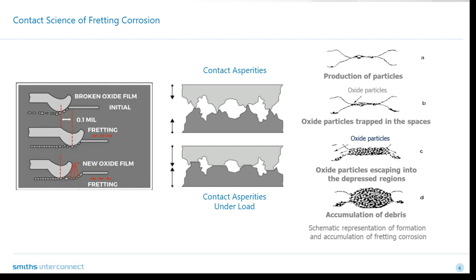When a fretting motion is induced, the noble coating, gold, is worn away and the nickel is exposed. As the fretting repeats, the oxide layer is wiped away, new oxides form, and the cycle begins again. As the process continues, the oxide particles get trapped in the depressed regions of the asperities, which build up and increase the resistance. Eventually, the accumulation of debris becomes great enough to prevent current from flowing between the electrical contacts and leads to contact failure.